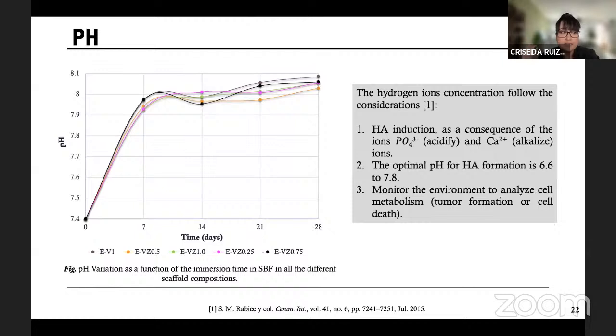The simulated body fluid, SBF, affects the dissolution of the scaffolds and releases calcium and phosphorus ions due to local saturation. This phenomenon generates nucleation and hydroxyapatite precipitation. The higher the saturation, the higher the apatite formation will be, and the lower the saturation, the more the hydroxyapatite formation will be inhibited.